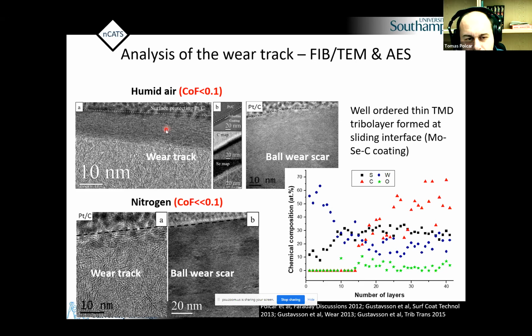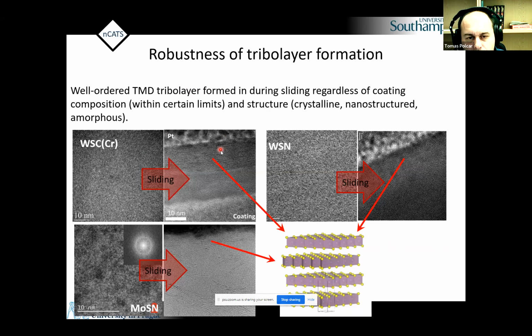And you may say, perhaps this is because we have initially this kind of platelets, which look like 2D platelets in the material, so they may be separated mechanically. But actually it's not the case, because if you look at what happened with a fully amorphous initial material, so we can produce this material by sputtering amorphous, we can combine them with chromium, with nitrogen, it's very robust. Always when you slide them, you will end up with beautiful ordered layers. And if you really do details, that's what you see on the top. You see, for example, in this case, tungsten disulfide, or in this case, molybdenum disulfide layer. And this produces low friction, and indeed these coatings are extremely useful because they can reduce friction to a level which is typical for oils, for example.